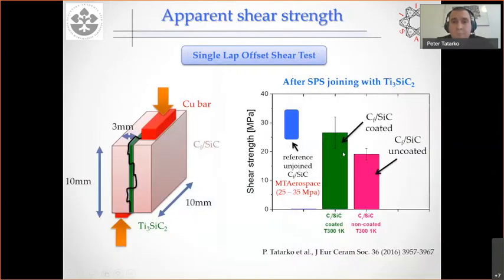Coming to the mechanical performance of these joints, here are the values. It's between 25 and 35. This was the value we got from the supplier, MT Aerospace, as a reference sample. You can see that when we used coated samples, the strength of the joint was, this is apparent shear strength, I should say. And for these coated samples, we got the strength just right in this interval of the reference sample.